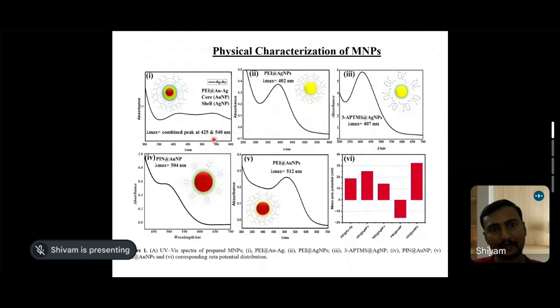One was at 425, which is characteristic of silver, and another at 540 nanometers, which is characteristic of gold. And you can see there is a core-shell structure having gold nanoparticle in the core and silver nanoparticle in the shell. Further, I stabilized silver nanoparticles with PEI via microwave processing, which showed an SPR characteristic at 402 nanometers. Similarly, silver nanoparticles stabilized with 3-APTMS showed SPR at 407 nanometer. Polyindole-stabilized gold nanoparticles demonstrated absorbance at 504 nanometer. Polyethylenimine-stabilized gold nanoparticles demonstrated absorption at 512 nanometer.